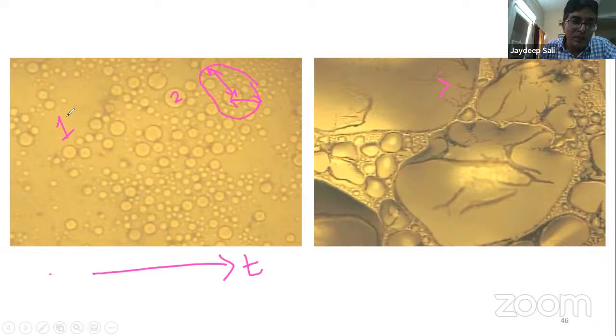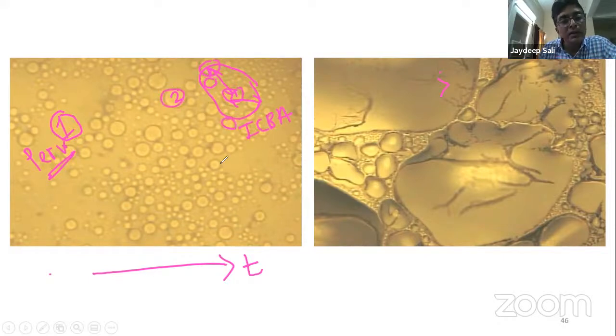Now the first solvent, suppose it contains the perovskite precursor. If the second solvent, these drops, contain the ICBA precursor, then just by controlling the size of these droplets during thin film formation, and we have seen that we can control the size of the droplets by precisely monitoring the acetone content in the microemulsion, we can control the distribution of this second component in the first component.